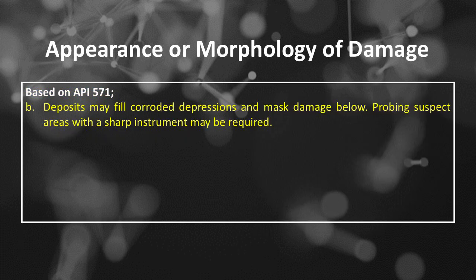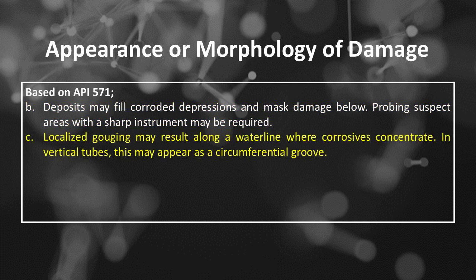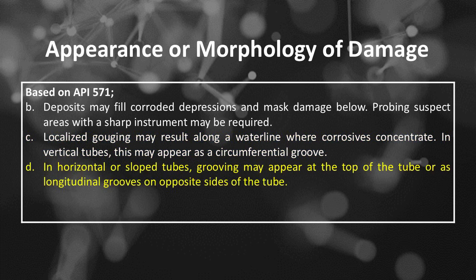Number B, deposits may fill corroded depressions and mask damage below. Probing suspect areas with a sharp instrument may be required. Number C, localized gouging may result along a waterline where corrosives concentrate. In vertical tubes, this may appear as a circumferential groove. Number D, in horizontal or sloped tubes, grooving may appear at the top of the tube or as longitudinal grooves on opposite sides of the tube.